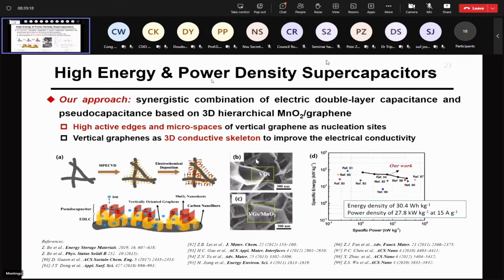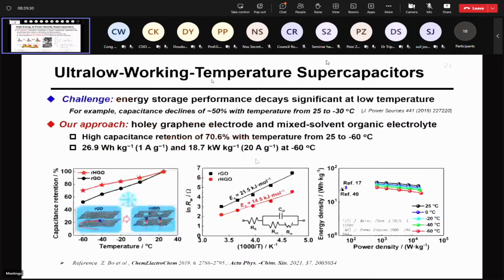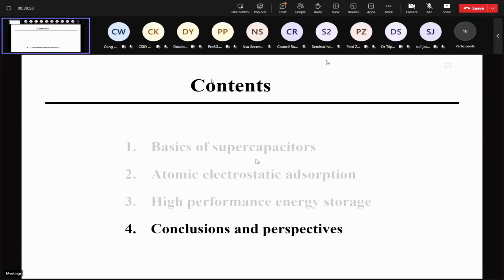This is the work where we combine the traditional EDLC and the pseudocapacitors to achieve both high power and high energy density supercapacitors. In this paper, we reported ultra-low working temperature supercapacitors. We use the holey graphene electrode and mixed-solvent organic electrolyte to expand the working temperature window of the supercapacitors.